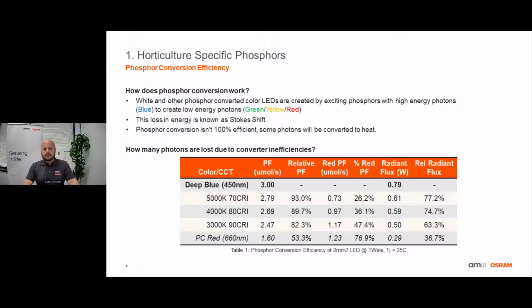So how many photons do we lose during phosphor conversion? Well, table 1 shows the relative photon flux of some of the commonly used CCTs and CRIs, LEDs that are available, versus a deep blue 450 nanometer LED that these LEDs would be converted from. Now, for this comparison, we're looking at 2 square millimeter size die that are being driven at 350 milliamps, so approximately 1 watt, and at a junction temperature of 25 C. So in this condition, we would expect a 450 nanometer blue LED to emit approximately 3 micromoles.